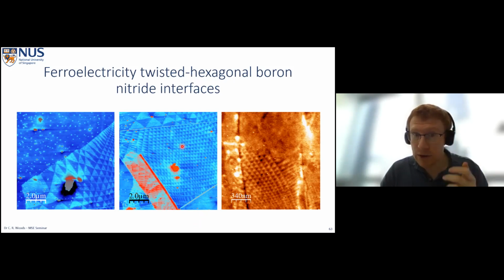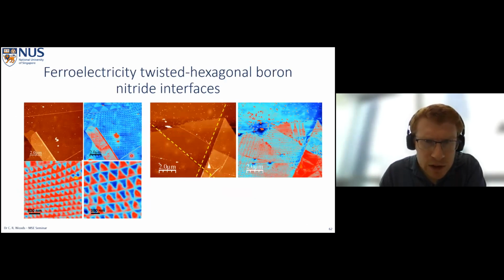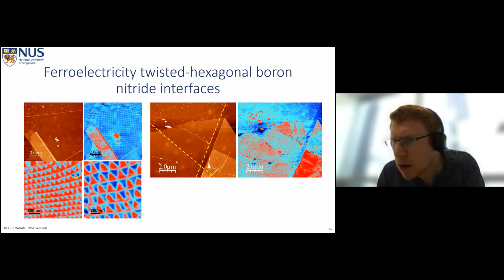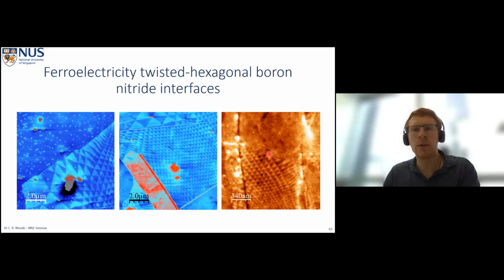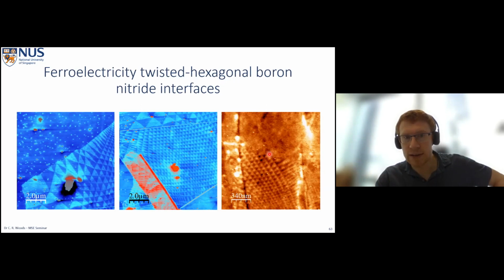And certainly we do see some regions of uniform. I don't think I include too much on it here, but we see some fairly uniform regions in this sample. But for this, we were looking really just at understanding what we're looking at and what it is. But I think it is possible to tweak this situation by just changing the number of layers and maybe how precisely you put them down, or how many layers on each side. You can tweak the macroscopic strain within the layers. Right? Does that make sense?